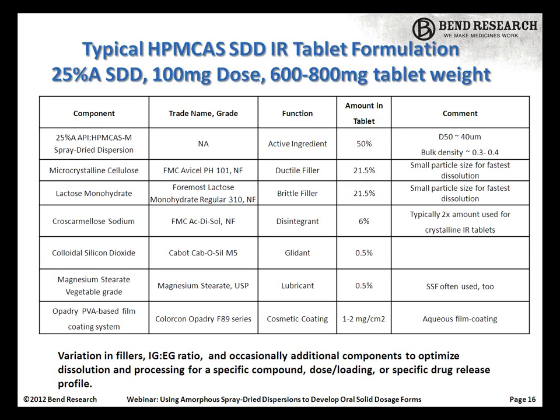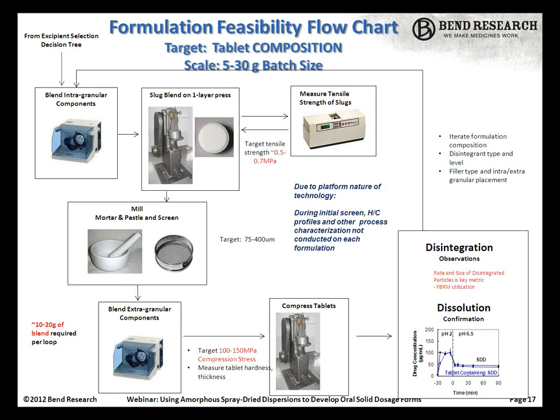The next slides I'm going to talk about are our process and formulation development. I've got some flow charts here that we utilize. We normally are limited in the API amount that we have available. So I mentioned earlier, we do break up the selection of the tablet composition from the process development somewhat cleanly. So this first slide here is kind of a screening mode. These would be small batches that we make at bench scale. We don't use actual automated processing equipment for most of this. This has been developed over time as what we can do for screening.